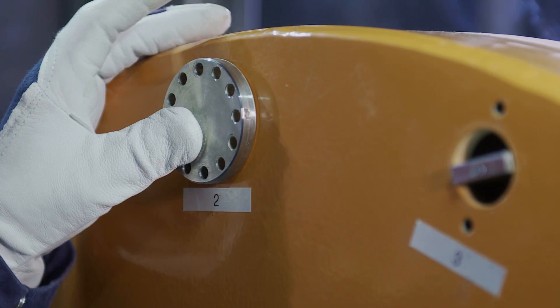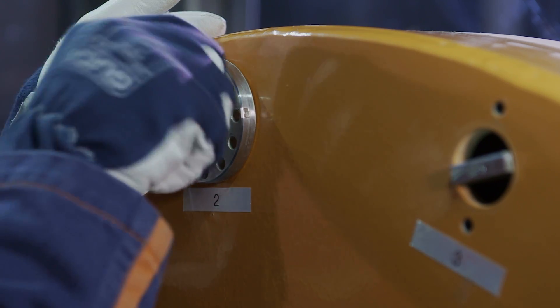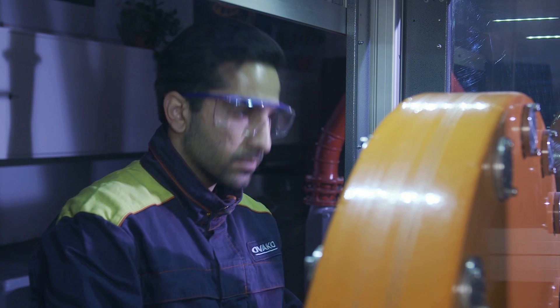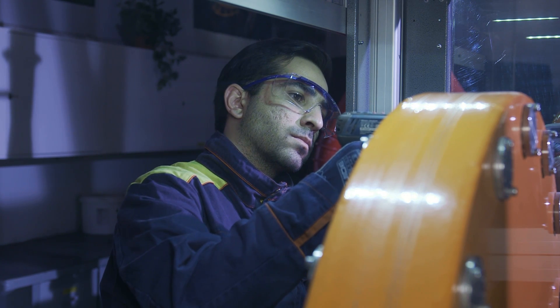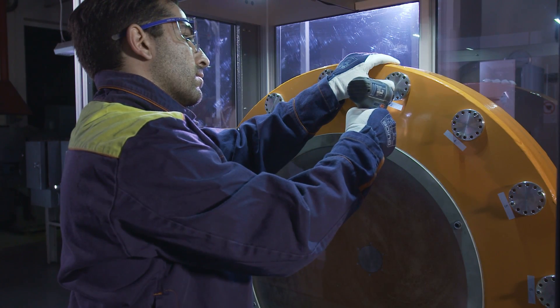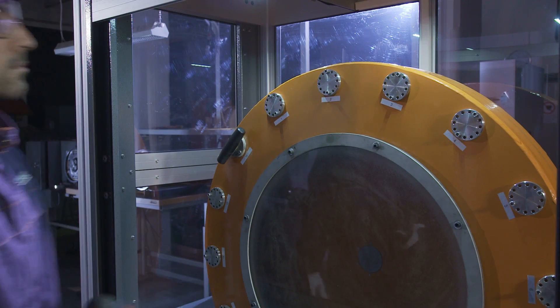One important aspect of this wear test configuration is to have the sample holders outside the test environment and expose the samples directly to the wear condition without the interference of the holders, which brings it closer to the real-life condition. The simple design of the samples gives the possibility to manufacture them from any production shape like round bars, hot rod, tubes, and so on.